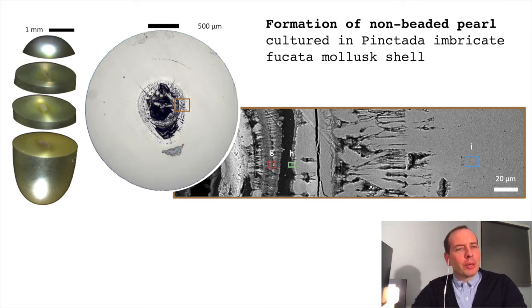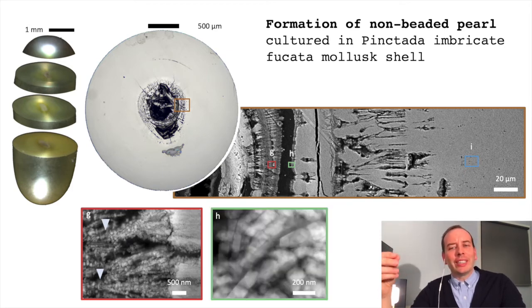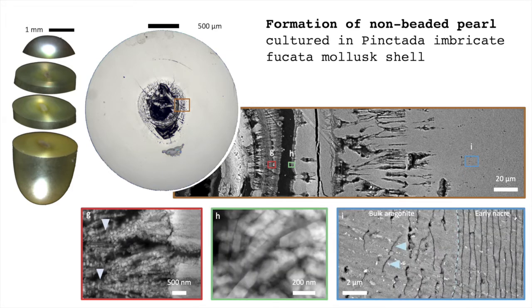The formation of pearls begins with an aggregation of nanoparticles that accumulate with higher density. It's not until a continuous organic sheath forms that we see the first nacre layers. Here we can see the earliest nacre layers on the far right image. These nacre tablets are forming within interlamellar organic sheaths that act as the main patterning agent between layers.